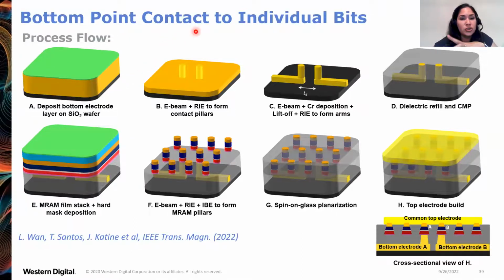I'll describe the bottom point contact. You start out by using E-beam lithography to define the metal pillars here, and a second E-beam lithography step to make the contact arms that go out to the contact pads. And then we do silicon oxide dielectric refill and chemical mechanical polishing to make sure this surface is very, very smooth for the MRAM stack deposition with the hard mask on top.